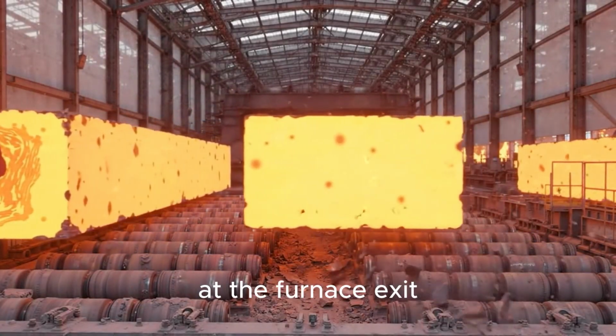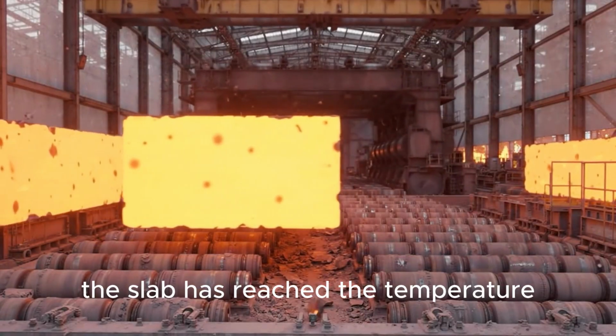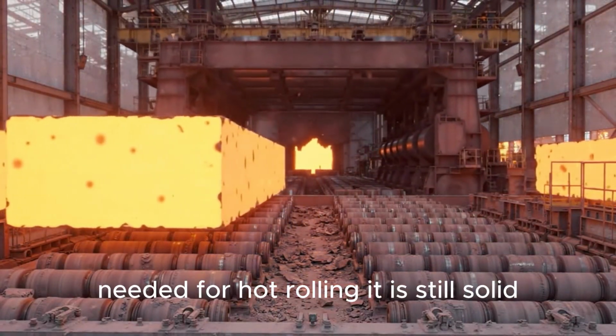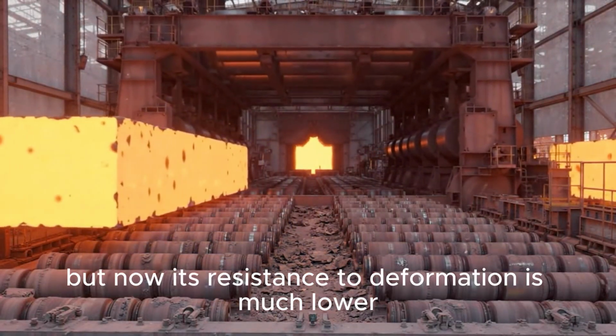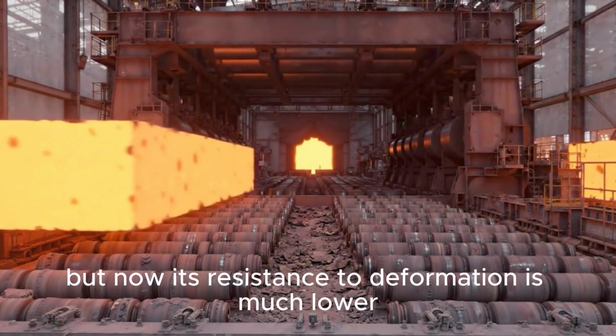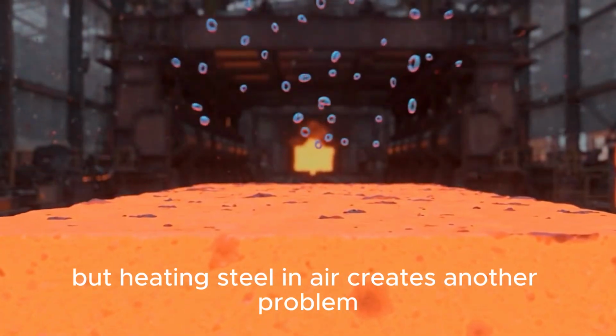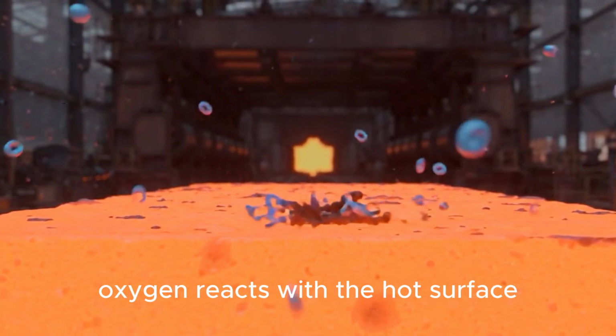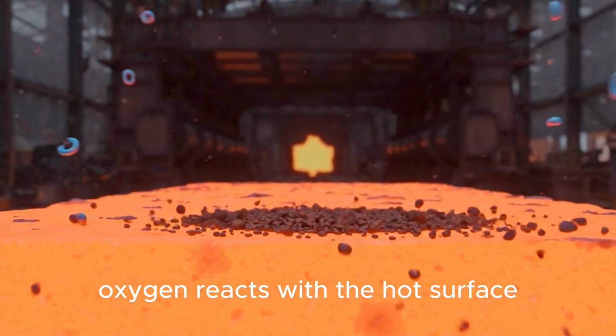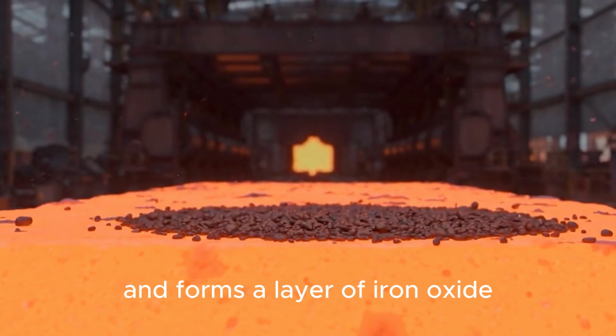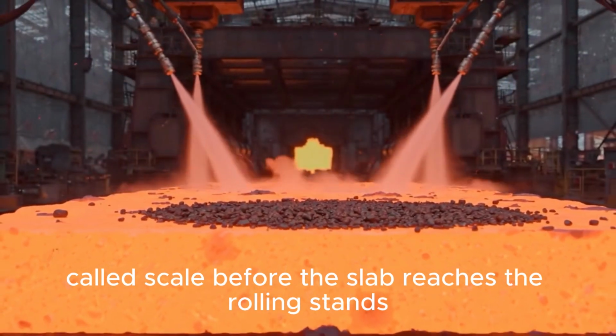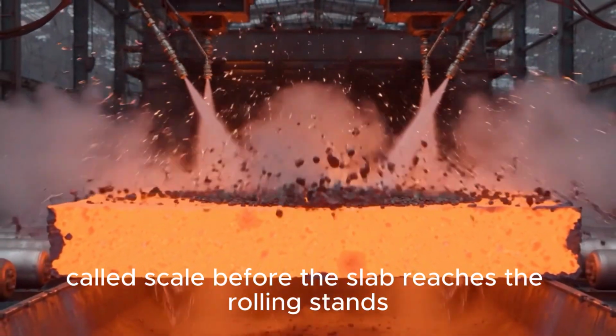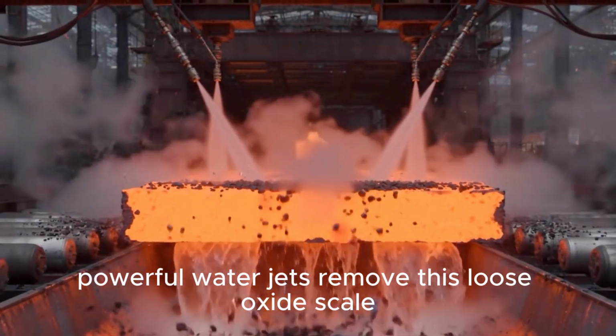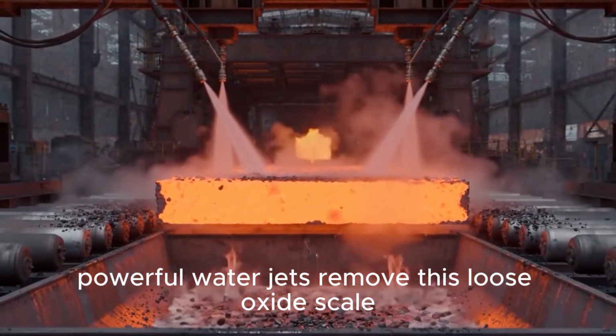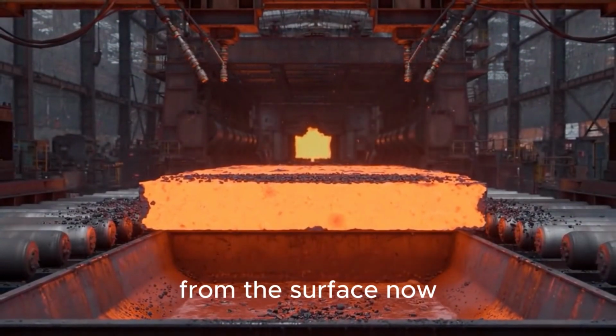At the furnace exit, the slab has reached the temperature needed for hot rolling. It is still solid, but now its resistance to deformation is much lower. But heating steel in air creates another problem. Oxygen reacts with the hot surface and forms a layer of iron oxide called scale. Before the slab reaches the rolling stands, powerful water jets remove this loose oxide scale from the surface.